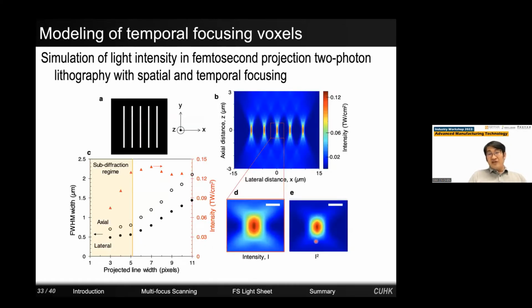Another advantage of this system is the voxel aspect ratio is not the conventional Gaussian beam aspect ratio 1:3. Instead, it's 1 to 1.25. And this is because the voxel or resolution of a temporal focusing system is not determined just by the Rayleigh's criteria. In other words, wavelength and numerical aperture. It is also simultaneously determined by the pulse width. The narrower the pulse, the thinner the light sheet.